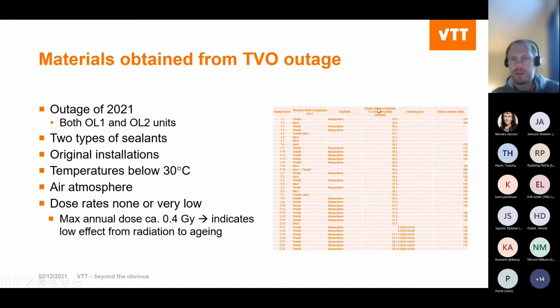Here you can see this is in Finnish, the heading here, but here you can see the temperatures, and all temperatures at which these sealants were exposed were below 30 degrees. The atmosphere was air, and regarding dose rates, most of the samples didn't see any, and those which saw some radiation, the dose rates were very low. So the maximum annual dose calculated from the highest dose rate was about 0.4 grays. So this is a clear indication that the effect from the radiation on the aging of the sealants is rather low.